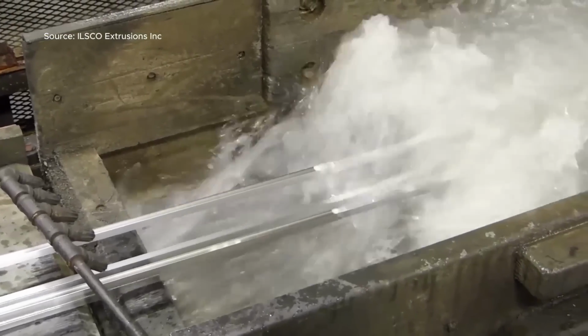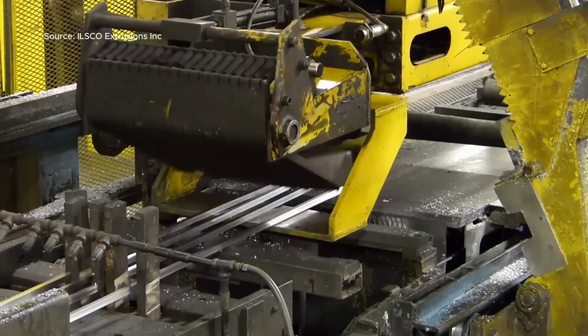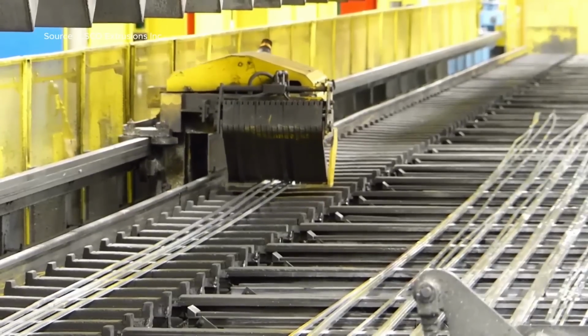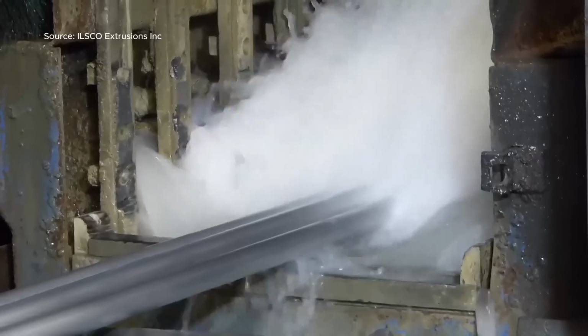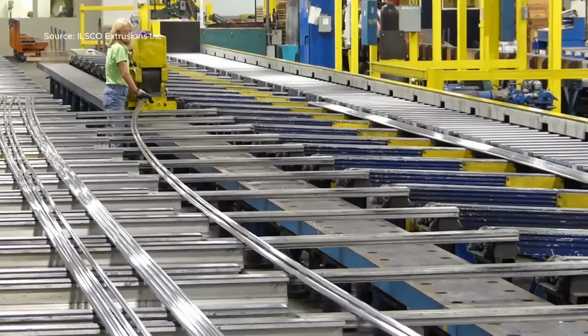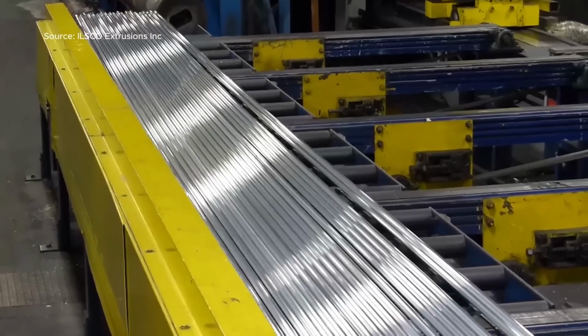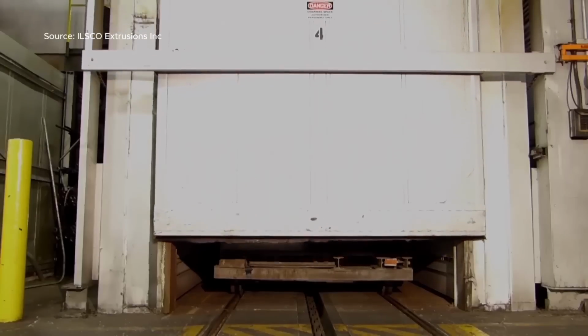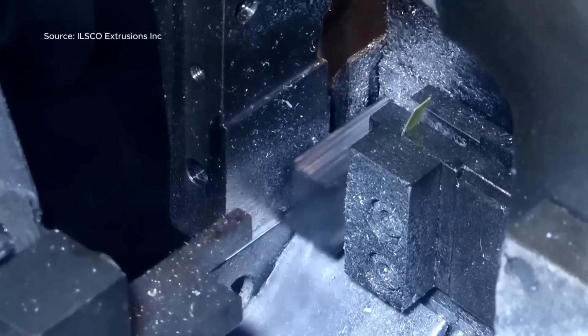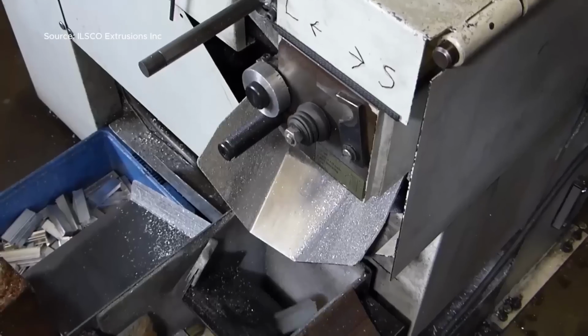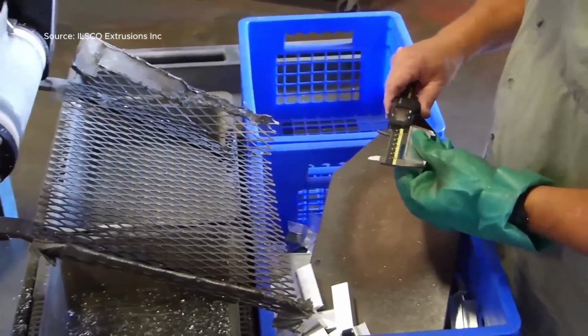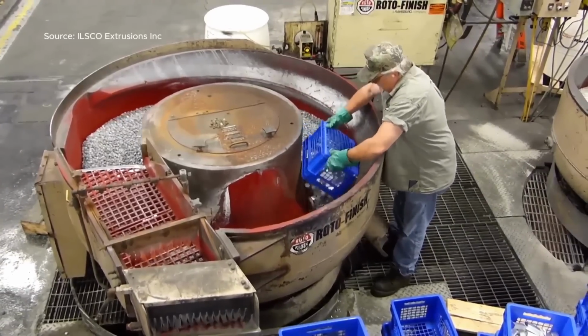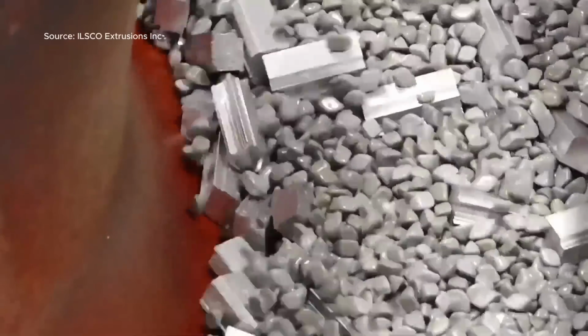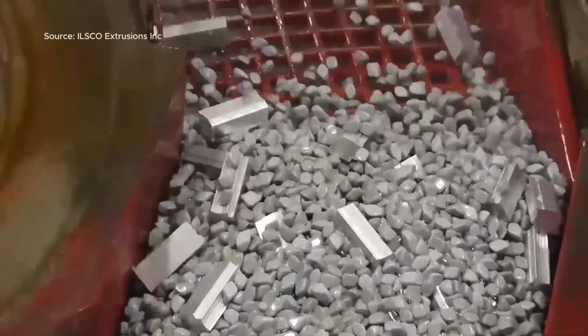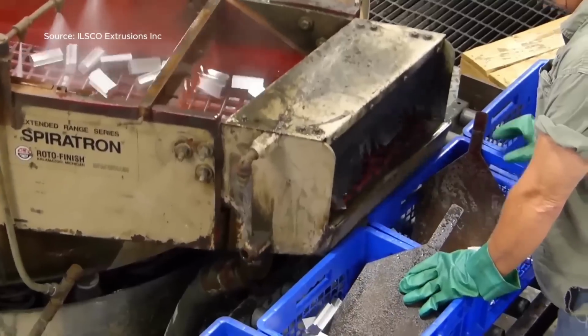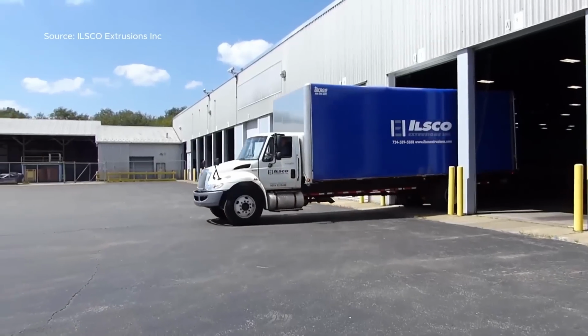This is how aluminum extrusion takes shape under pressure, heat, and control. Aluminum logs are sliced, heated to 900 degrees Fahrenheit, and forced through a steel die by a hydraulic press. Each profile is quenched, stretched, and aged in ovens to meet exact specs. Infrared cameras monitor billet exit and quench temperatures with tight tolerances. CNC saws trim parts to custom lengths, while vibratory finishers smooth the surface. It's pressure, timing, and heat, refined into repeatable accuracy every time.